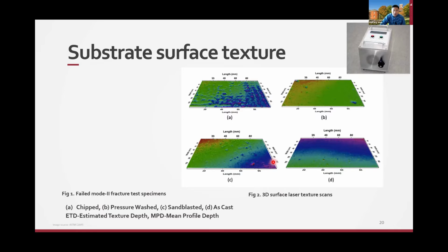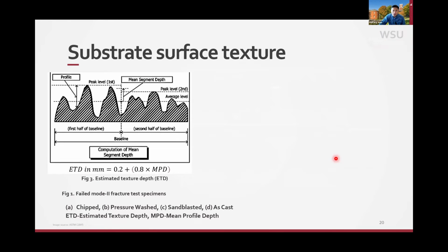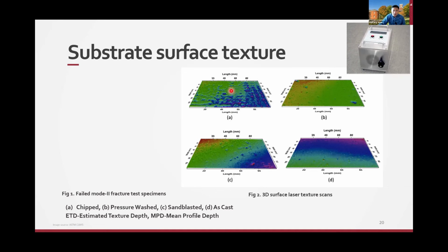Then in terms of the roughness of the surface, especially the concrete substrate, we want to measure the texture, how rough it is. So we use laser scanning to scan the surface. You'll see the chipped surface preparation gives you the highest surface texture or roughness, followed by sandblasting, then pressure washing and as cast. That explains why the shear, which is sensitive to the texture, is higher for the chipped method and sandblasting. So that's from the laser scanning.